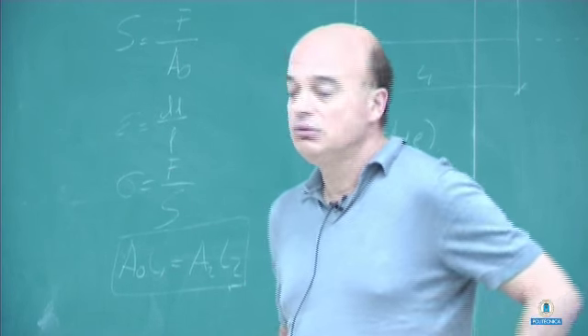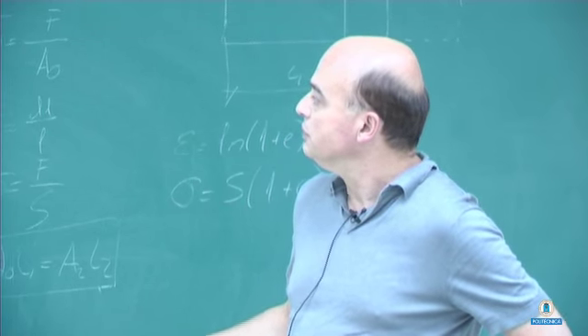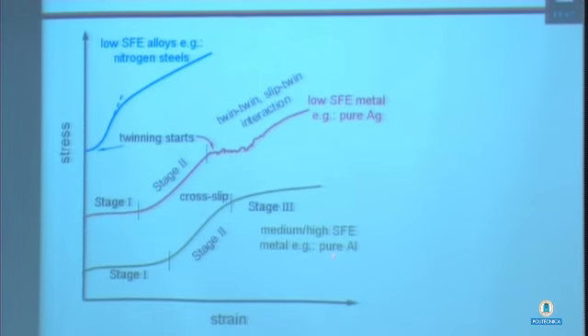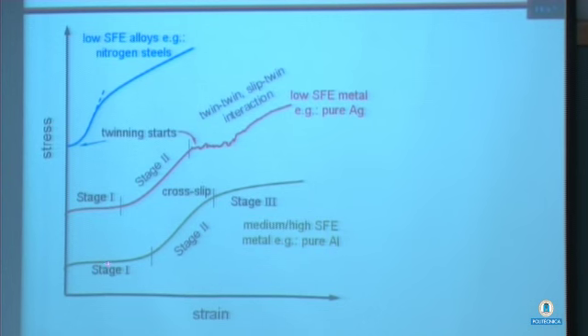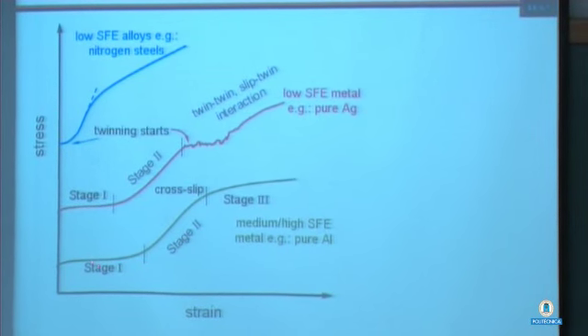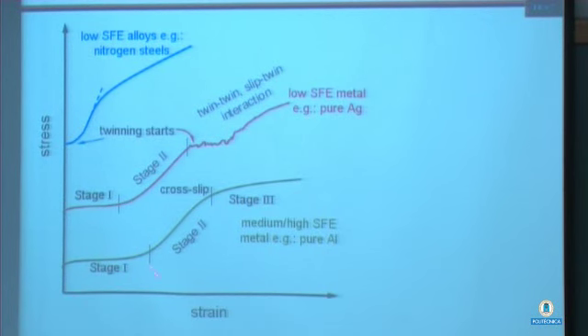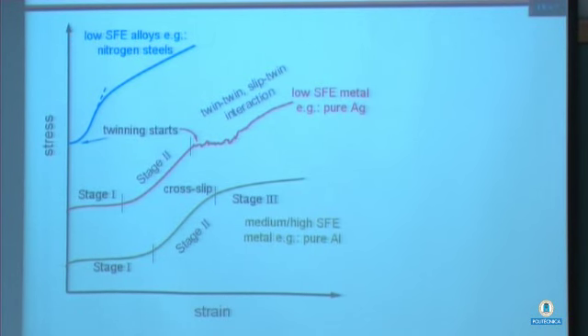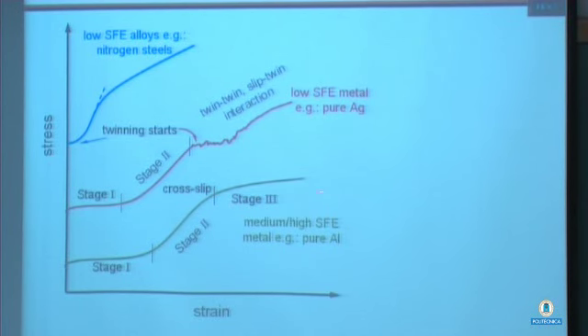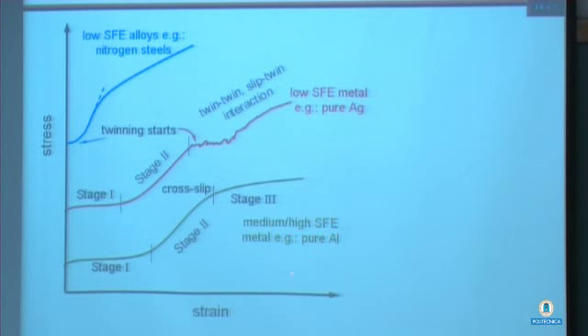Now, going back to the importance of deformation, if you look at pure metals, medium or high stacking fault energy metals like aluminum, you get stage 1 deformation. This is typically considered single slip. Stage 2 is where slip bands interact, and in stage 3 you start getting cross slip and a little softening. That's the typical stress strain curve for a pure metal like aluminum, like nickel, with a medium to high stacking fault energy.